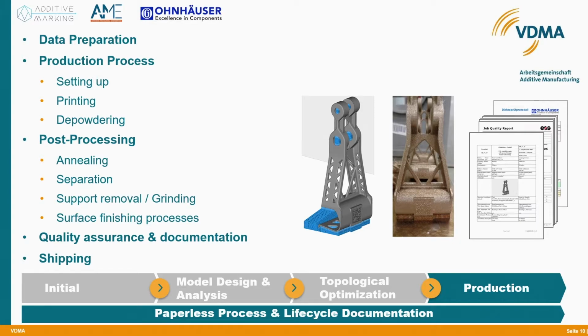The printed marking ensures that the parts are assigned to the correct orders. This avoids confusion. As each part has supports, they have to be removed by hand and the leftovers have to be ground for a clean surface. Different processes are applied to refine the surfaces depending on the application. These are typically blasting, vibratory grinding, and electropolishing. Depending on the requirements for the part, these processes can also be combined. For higher accuracy, as well as for threads and fits, CNC machining is used. This is usually a milling or drilling process. The quality assurance department checks compliance with the acceptance criteria specified by the customer before a part is delivered. After successful inspection and subsequent documentation, the parts are shipped to the customer.